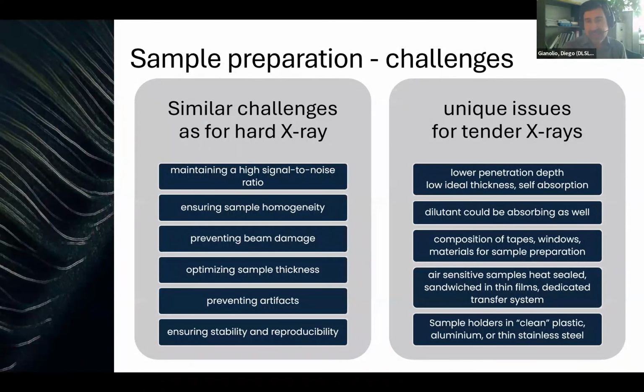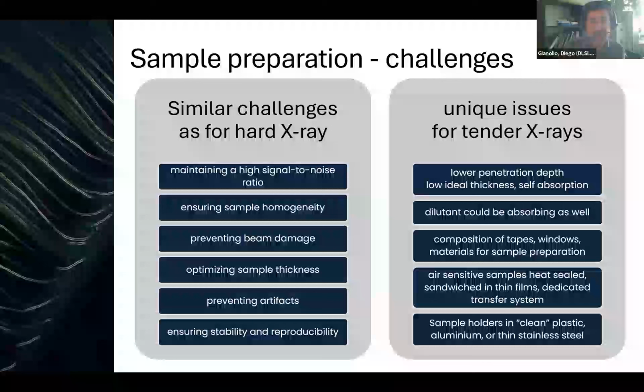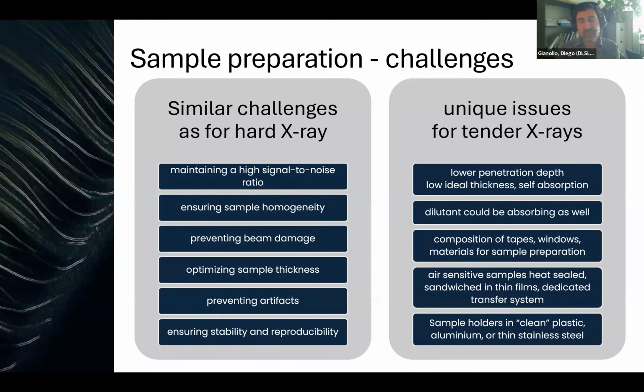And after these more technical issues, we try to focus more on what could be interesting for the users and what type of guidelines we can give them. So we discussed the sample preparations, and we found out that, of course, there are challenges. Some of them are similar to the preparation that you need to do for hard X-ray beamlines, and others are a bit more unique issues that are common only for the tender X-ray range. Some of the similar challenges are to be able to get a good signal to noise from the sample. This means making sure that the sample is homogeneous, that the sample is not changing while we measure it, so preventing the beam damage, that the thickness of the sample is optimized, and that there are no pinholes that could cause artifacts, and ensure stability and reproducibility.